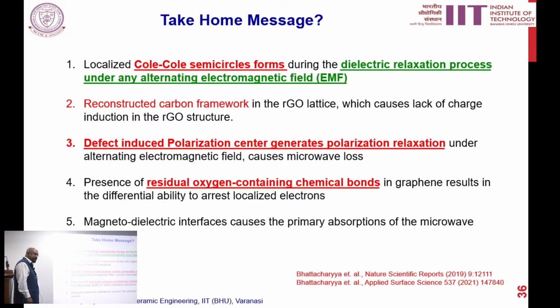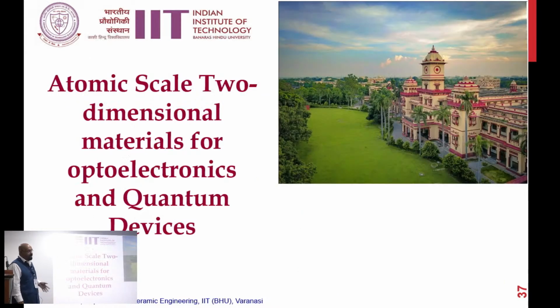So what is our take home message from this hybrid engineering structure? A few things, like the dielectric relaxation process under an AC electric field, are creating some localized Cole-Cole semicircles, and those are primarily responsible for the absorption. Along with this, they have a reconstructed carbon framework, the graphene. When one carbon atom goes out, what happens? They have some unsaturated bonds, right? Those unsaturated bonds have some unsaturated electrons. So localized electron concentration increases, followed by defect induced polarization centers. The electrons under the AC magnetic field just dance like anything on that specific defect, so they just change their polarity. Followed by that, the residual oxygen containing chemical bonds. Those are all primarily responsible for our radar absorbing properties.